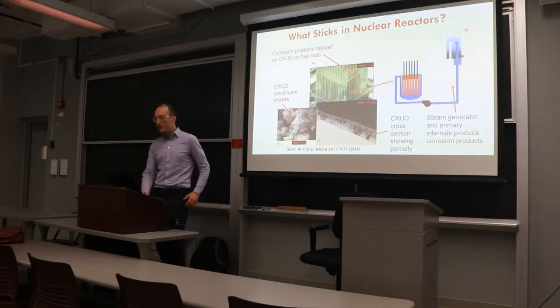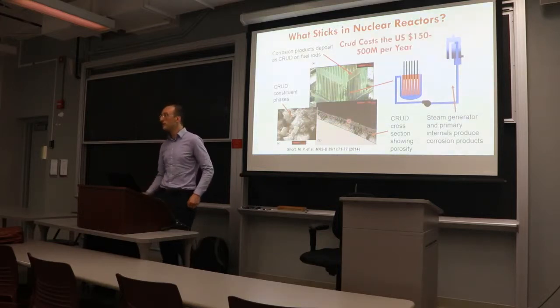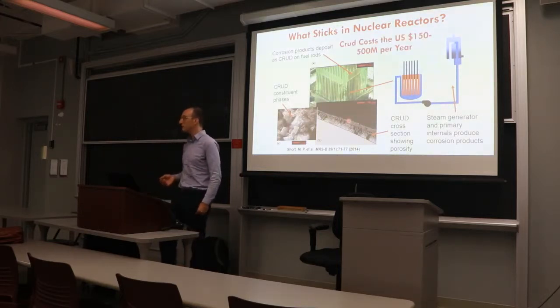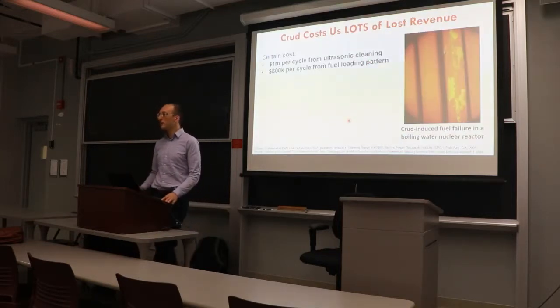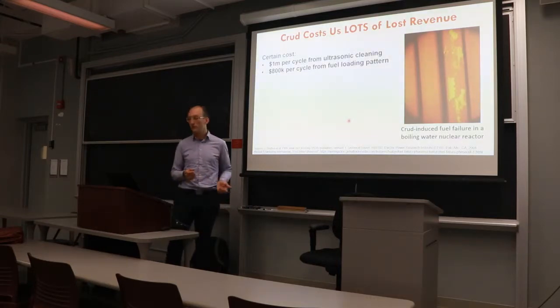It's corrosion products that come from elsewhere in the reactor, like the piping and the steam generator, and plate out here on the fuel as this brown crusty stuff. It's 20 to 100 micron porous media that costs the industry between $150 and $500 million per year. And in this day and age, when natural gas is cheap and other renewables are over-subsidized, you can't compete like that. So the actual cost comes out to something like $1 million per fuel cycle per reactor from ultrasonic fuel cleaning, because that's how much extra outage time it takes to clean the crud off the fuel.